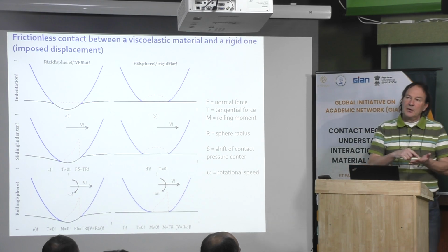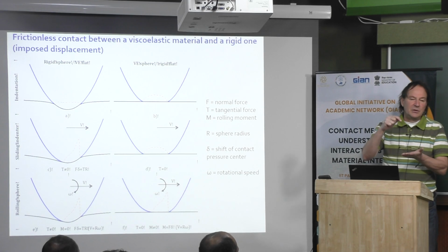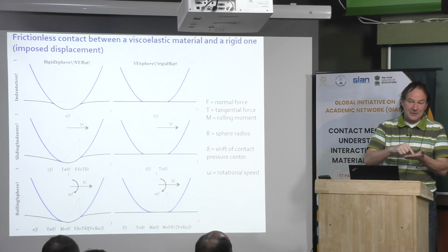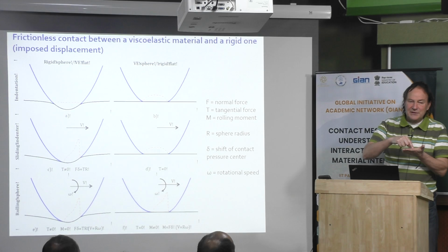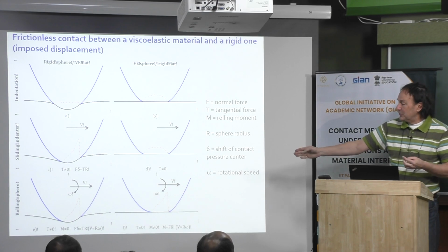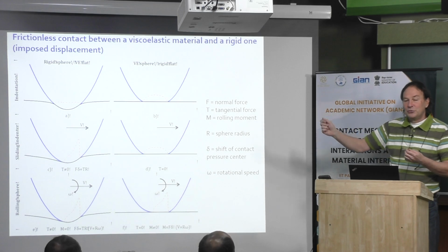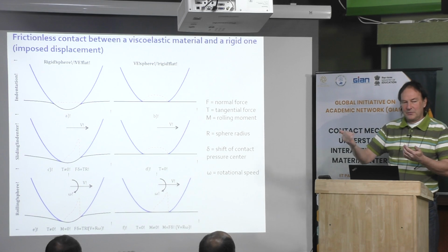It's because, in fact, the material is viscoelastic. At the beginning it's like a shock. We apply the load at t equals 0 in an instantaneous manner. Then the material has the initial Young modulus, which is very high. When you start to load the material, the Young modulus will decrease with time. So when you start to load the front material, it is elastic with a very high Young modulus, and due to the loading it becomes softer and softer. This is why there is this dissymmetry.